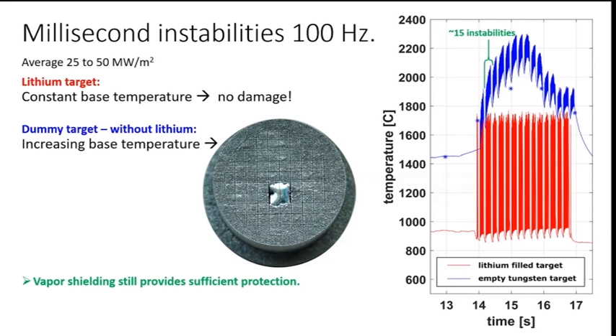So what can we conclude from this? Well, I would say first, vapor shielding still provides sufficient protection in this case. And keep in mind, the loading here is really quite severe. If you were to calculate this as an average heat flux, with a wide margin of error, I should say, it should be somewhere between 25 and 50 megawatt per square meter. It is in this ballpark.